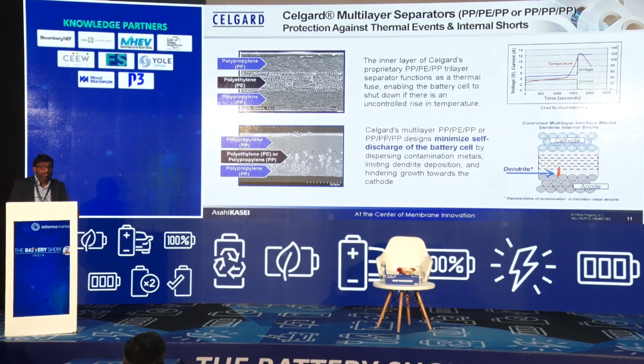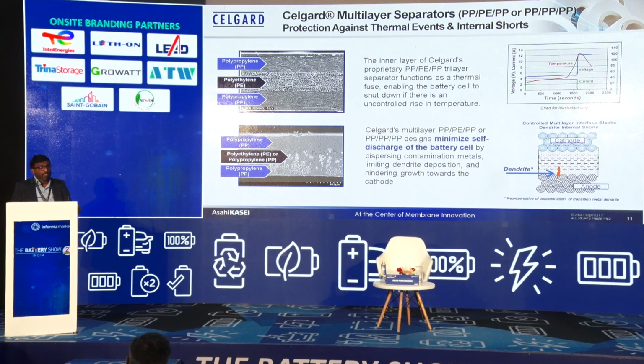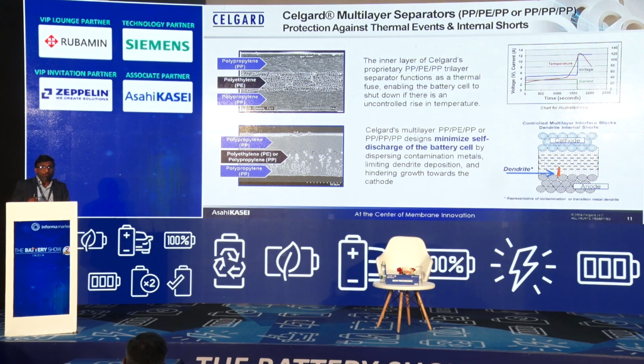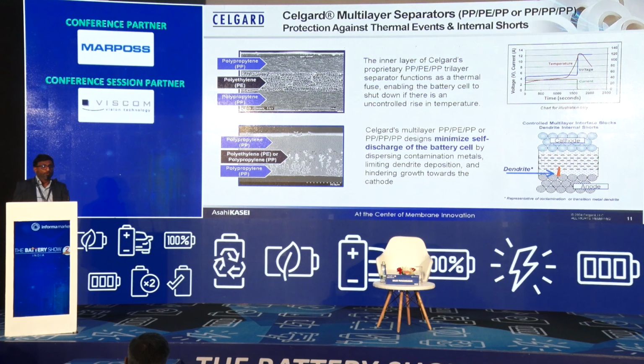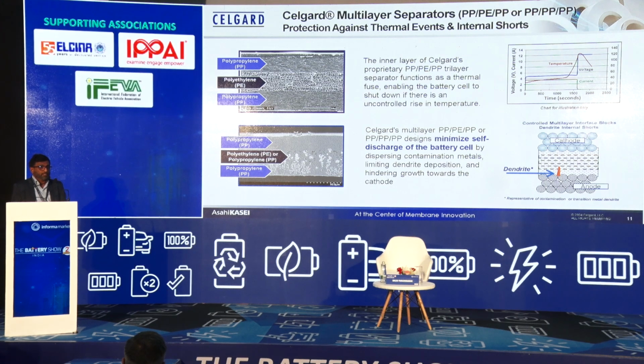So what is the advantage of this kind of dry separator? One advantage is that you can laminate this material. That means you can put multiple layers of films together. For example, if you want to put a polyethylene film and 2 polypropylene films, it is possible. The minimum total thickness we can do is 12 micron. That means we can put 4 micron for each layer.